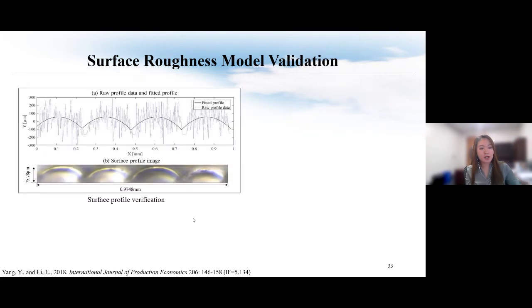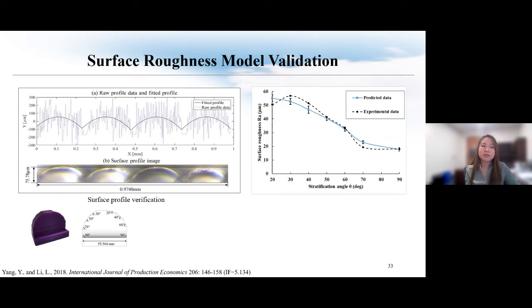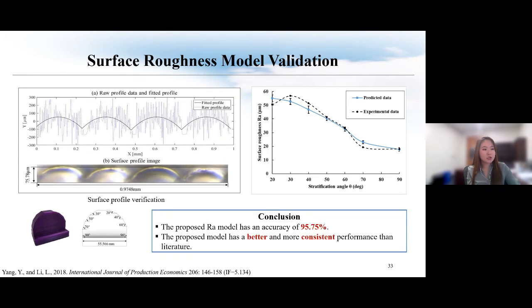And then we use the microscope to actually look at the surface profile, and we observed staircase errors. And then we used this geometry. This is unique because it has multiple surfaces with different angles, so that we can validate our model for different angled surfaces. And we also compared our results with literature. So our model turned out to have an accuracy of almost 96%.